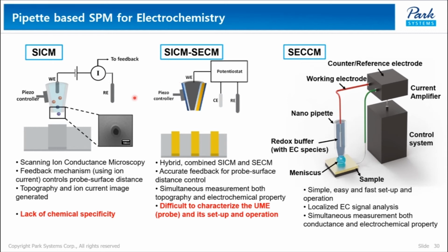SICM can help us get the topographical information of the sample surface using the ion current signal between the pipette end and the sample surface, but we cannot get the electrochemical information. But by adding an ultramicro electrode as a scanning probe and a potentiostat to the SICM, it transforms into a pipette-based SICM-SECM. In conventional SECM, it is a bit difficult to control the pipette-sample distance, thus reducing the reliability of the data.